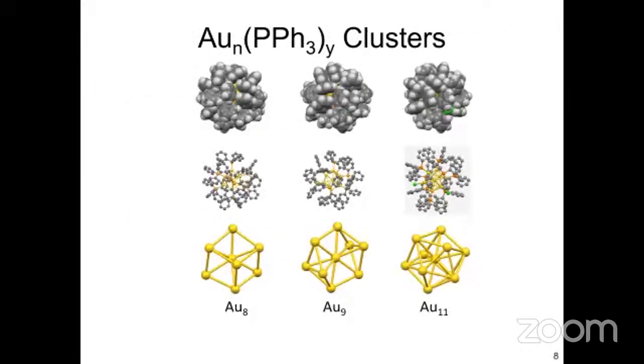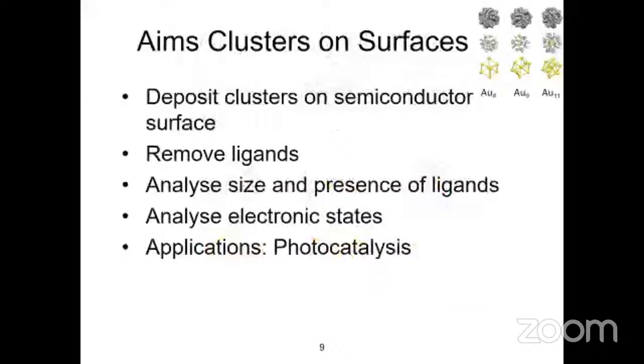The group we work with, as chemists, are producing gold 8, 9, and 11, exactly gold 8, 9, and 11. They measure and screen it by NMR and by different mass spectrometers. The purification is a bit difficult for this nanocluster to have it in precise atoms. We deposit them and we remove the ligands, because at the end we need access to the gold core of the cluster itself, and we use it for the application.